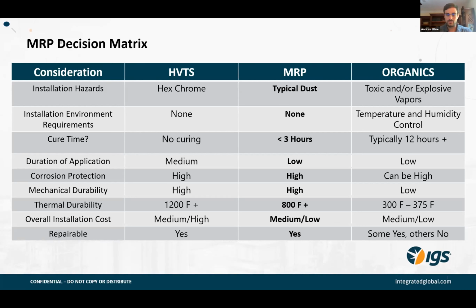The HVTS layer has a similar thermal expansion rate to the carbon steel, and the top coat is impregnated into that coating. So now you're not dealing with that same thermal mismatch anymore, as Jan mentioned. So it's much more robust to thermal cycling and things like that. Also talking about the overall durability. If I'm using aggressive cleaning methods, if I'm taking scaffolding in there, in and out, other things that can cause that, the MRP, because that top coat is impregnated into that HVTS layer, you have a higher resistance to erosion and physical damage than you do with some of the other coatings. That being said, HVTS is going to be the best option if you have high erosion. The MRP is still a compromise in there.